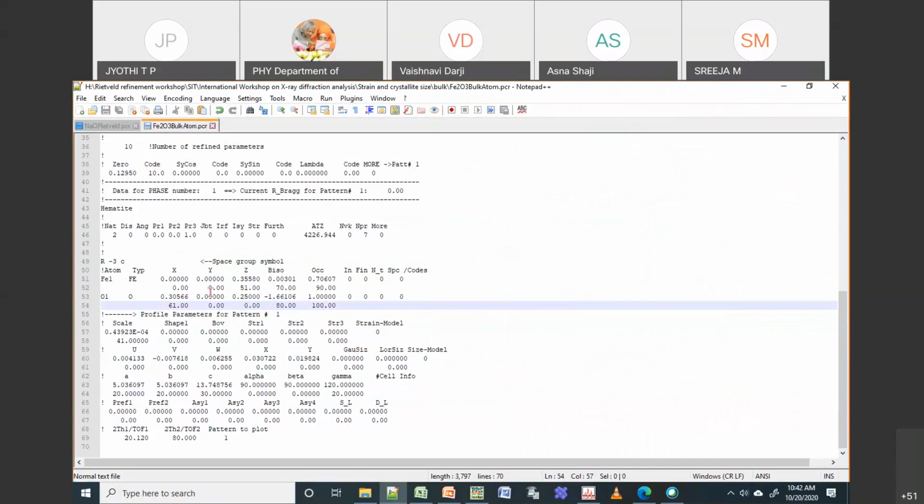Okay, also there is one thing which you need to take care of. When you're doing a Rietveld refinement on X-ray diffraction data, don't refine these values for your oxygen, fluorine, all those things, because they are less sensitive, since these are very small and very light atoms. So for hydrogen and oxygen, you should not refine the occupancy data because they are much less sensitive for X-ray diffraction.